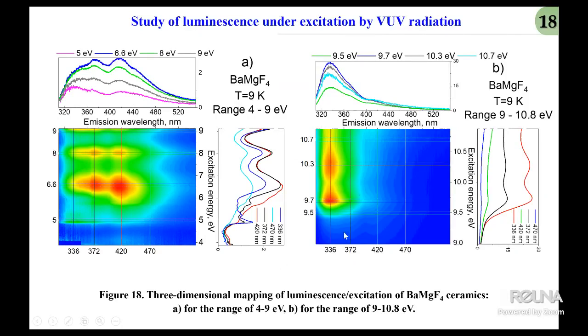Figure B shows that in the high energy region the spectral behavior changes significantly. The main contribution to emission comes from the band at 336 nanometers, while the intensity of the 372 nanometer band increases.